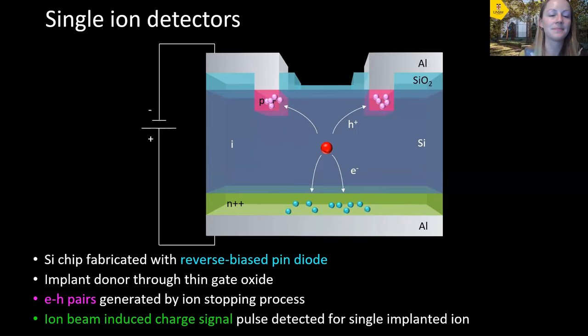And this detected charge signal is proportional to the energy with which you implant the ion into the silicon. And it allows us to basically trigger the implantation event of our donor qubit. And so we would know that we've implanted one donor and it's time to go to the next implantation site to make an array, for example.